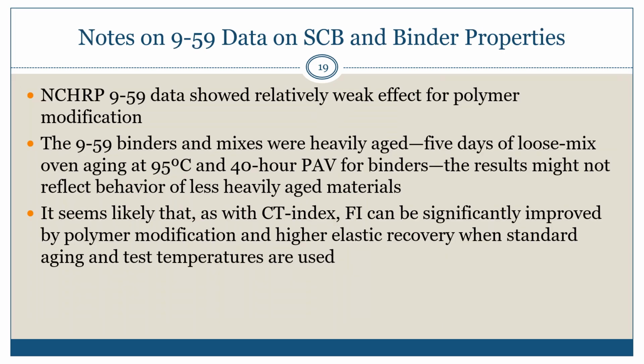I wanted to make a few comments about the results of the 959 research and the SCB research, binder properties and polymer modification. Now, in this research, we saw a relatively weak effect for polymer modification and for things like elastic recovery. However, we think that this was because the binders and mixtures were so heavily aged.